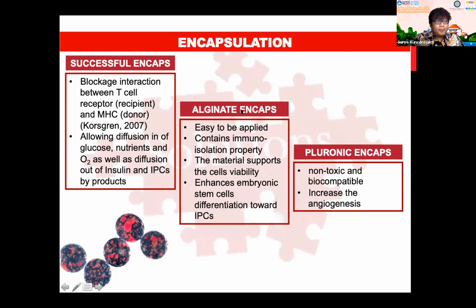In this study, sodium alginate was used as the encapsulation material since it is easy to apply and has immunoisolation properties. And another reason why we use sodium alginate: it can support cell viability and also enhance the differentiation toward the IPC. And how about the pluronic acid or pluronic encapsulation? The pluronic-based encapsulation was used as a double coating since it is non-toxic, biocompatible, and increases angiogenesis.